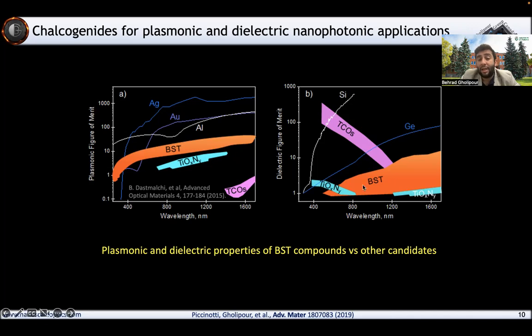Aside from that, you can see that as we go further and further into the infrared part of the spectrum, the chalcogenide material family really starts to get better and better as the transparent conductive oxides start to reduce and absorption kicks in for them. BST and these chalcogenide material families that you can tune very carefully give you a much better response at these wavelengths. And again, they're not single element materials, so you can tune them very carefully.